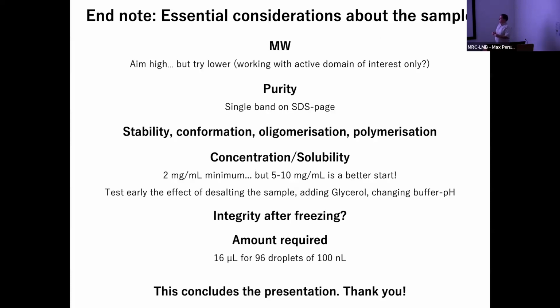And also simple things like testing the effect of desalting the sample. If you arrive with half molar sodium chloride in your sample, it's the same. It most likely won't work. So you want to see what's happening when you desalt. Maybe it will be less soluble, but then it's a balance between solubility and other factors. So I like to start with a sample with a relatively low proportion of salt. It's also so that the impact of the different vapor diffusion experiments is more there to start with, because if it's highly concentrated, you remember the experiment with the drops, and the water is pulled out in this equilibrium. If the drop is highly concentrated in salts, you won't have this equilibrium to start with.